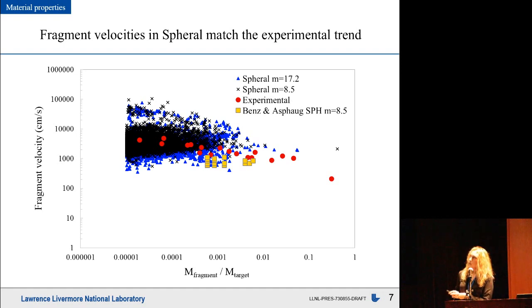The results by Benz and Asphaug underestimate the experimental trend line, and they also used an M parameter of 8.5, so we found it interesting that our results in spheral for using a parameter of M equals 8.5 didn't match what Benz and Asphaug were finding. Instead, we see that the spheral results for 8.5 shown in black have a concentration of smaller fragment masses for this fragment velocity range.